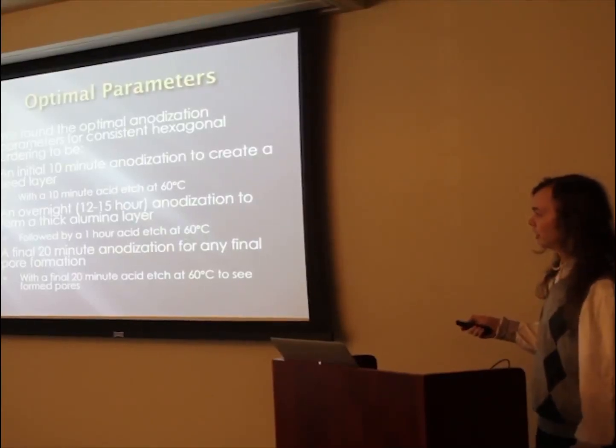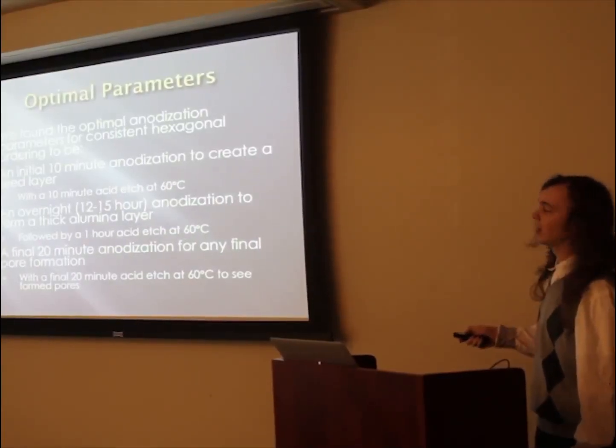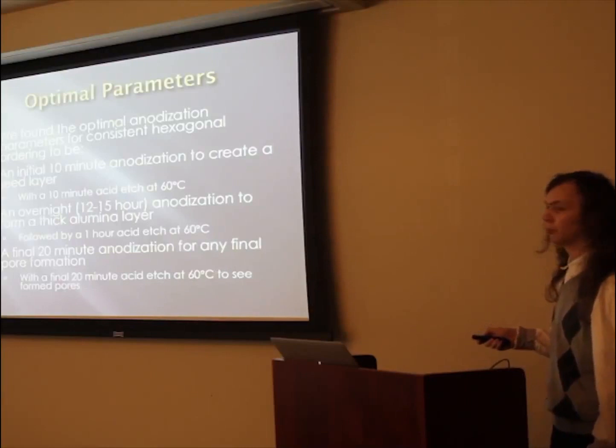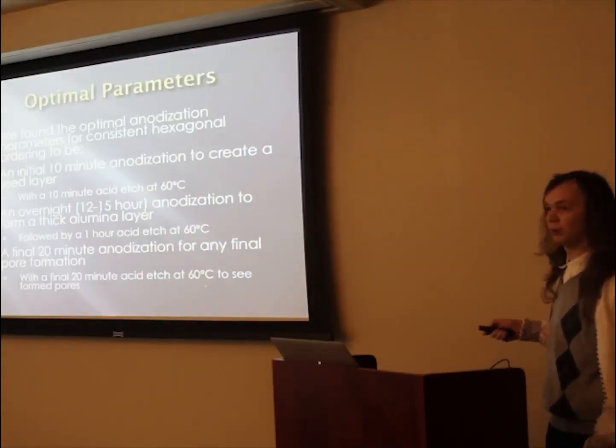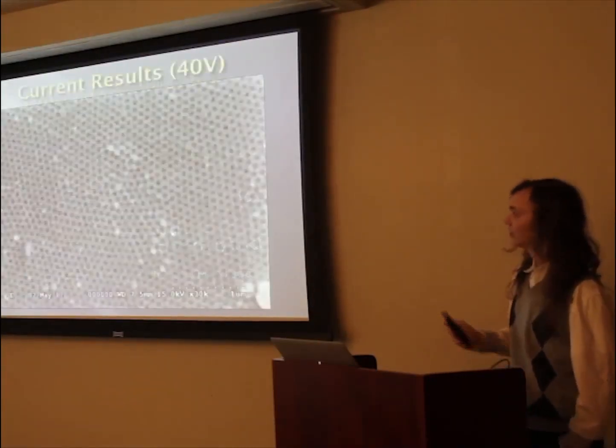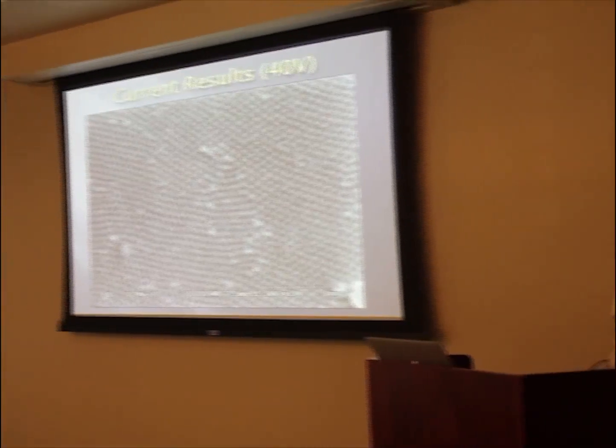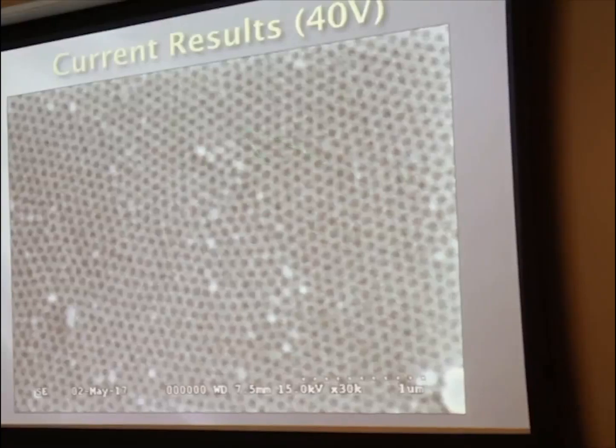You do a final 20-minute anodization for any final pore formation, and then to see it under the scanning electron microscope, where you need a conductive surface, we acid etch that top layer off to be able to look at it. So then, this is what we actually end up seeing. For a 40-volt sample, we see pretty small pores here that are pretty nicely distributed.